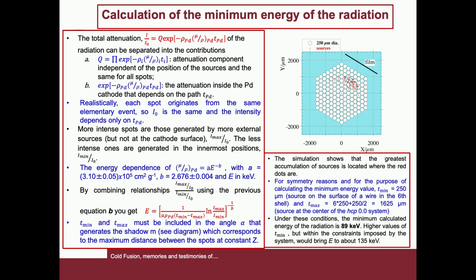Combining the ratios of I maximum and I minimum using the previous equation B, the energy value can be obtained, which, as we can see, depends on the difference between the shortest and the longest paths and on the ratio of the maximum and the minimum intensities. Obviously, T minimum and T maximum must be included in the alpha angle which generates the shadow, the one shown in the previous diagram, which corresponds to the maximum distance between the spots at a constant Z.